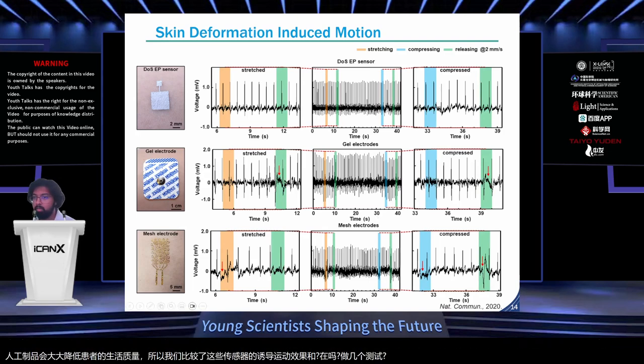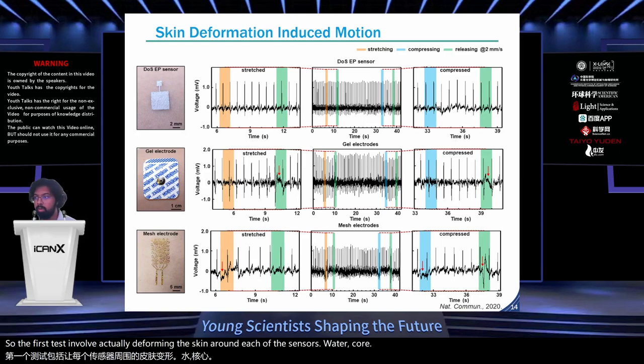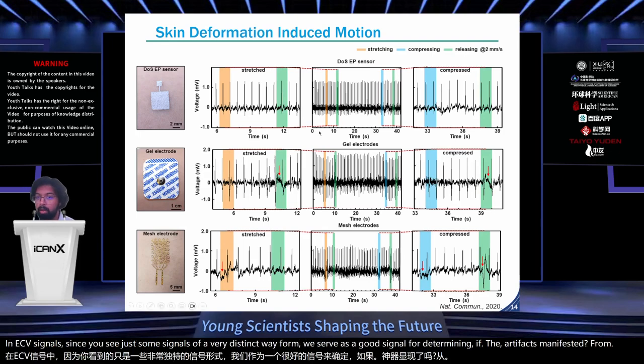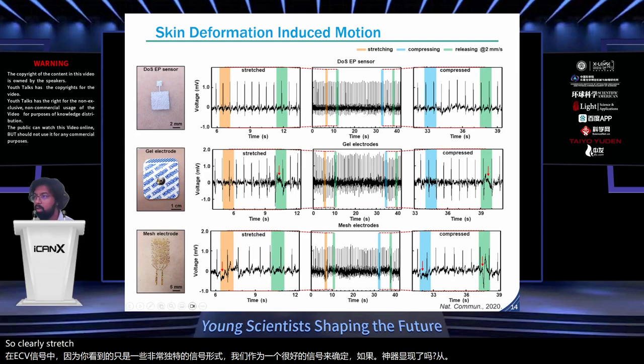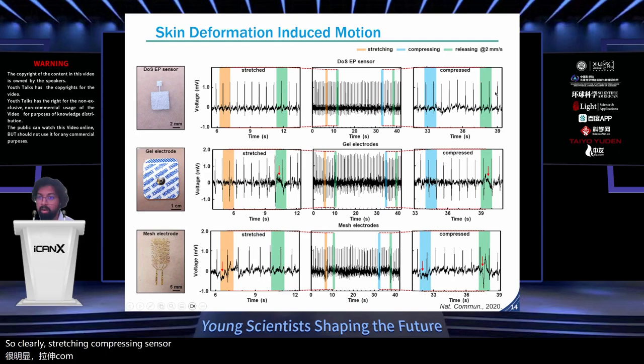The first test involved actually deforming the skin around the sensors while recording signals. Since ECG signals have a very distinct waveform, they serve as a good signal for determining if an artifact is manifested from the motion. Clearly, stretching, pressing the sensor, and releasing the deformation had no effect on the ECG waveform recorded with the DOS sensors, whereas the others are clearly affected.